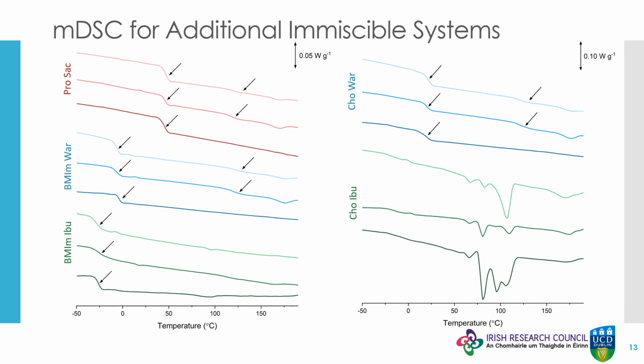Thermograms of the additional API-ILs, the order of the compositions is the same as in the PXRD results. Here, the phase-separated nature of the products is even more apparent than for the initial imidazolium-based API-IL from the presence of a second TG where that of the polymer is expected to lie. Again, the Cho Ibu example presents behavior inconsistent with the other examples. This is explained by Cho Ibu being only partially dried during the initial DSC drying cycle, and the residual moisture in the final heating cycle results in the API-IL partially recrystallizing into two distinct polymorphic forms. This has previously been observed for this API-IL and is mirrored in the thermograms of the spray-dried products containing this example.